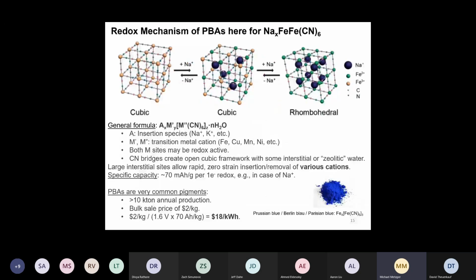Okay. So now let's see what happens if we change the amount of sodium that is intercalated in this material. The version shown here is iron hexacyanoferrate. So it's basically purely made up of iron on the different sites of the lattice, and the hexacyanoferrate groups span the cubic structure. So this is only one type of transition metal here. And if this structure doesn't contain any sodium, then iron would be in the 3+ oxidation state. Now, as we sodiate this material, so we put the blue balls in there, which is sodium, some of the iron will go to its 2+ oxidation state to balance the charge that comes from the sodium.